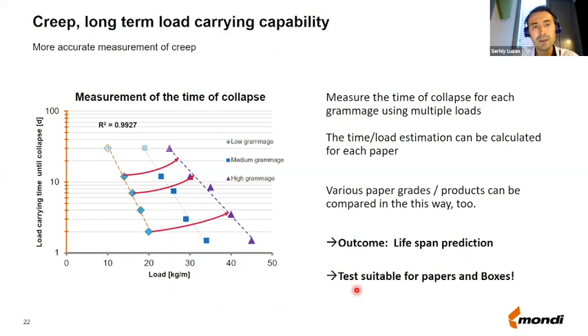So when you do a creep test, as I said, you would like to understand how long for each load the paper can hold this load. So you will take one paper grammage, and for this paper grammage, you will put different loads on the paper, and you see for how long this load will be held by this paper grammage. And then if you plot it in a logarithmic scale, you normally have these nice lines which show you the relationship between the load and the time. So if you repeat the same test for other grammages, you will have other lines.